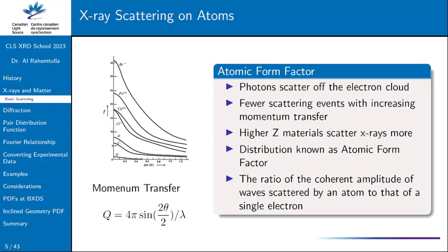So we're going to see stronger scattering with higher Z elements or lower elements on the periodic table. And the way scattering falls off with angle or momentum transfer isn't just like a smooth Gaussian. It might be hard to tell if you're far away, but these aren't very smooth curves. There's some sort of ripples and ridges to it. And that's not me just trying to draw something freehand. This is actually related to the electron orbitals that exist in the material.